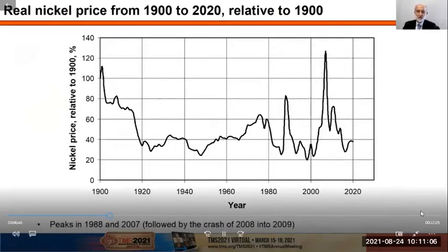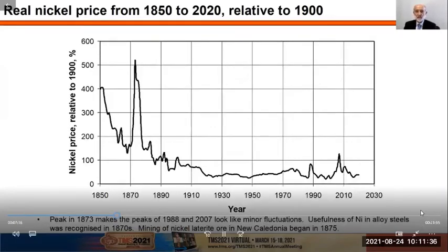If we correct the nominal nickel prices to real prices, taking into account the effects of inflation, as shown in the graph here, some of the things that really still stand out are the peaks in 1988 and 2007. Of course, that one was followed by the crash of 2008 going into 2009. However, if we extend that data series even earlier, and we look at figures from 1850, we can see that the peak in 1873 makes the peaks of 1988 and 2007 look like minor fluctuations.